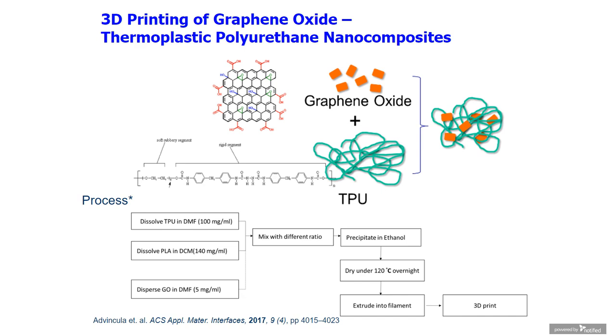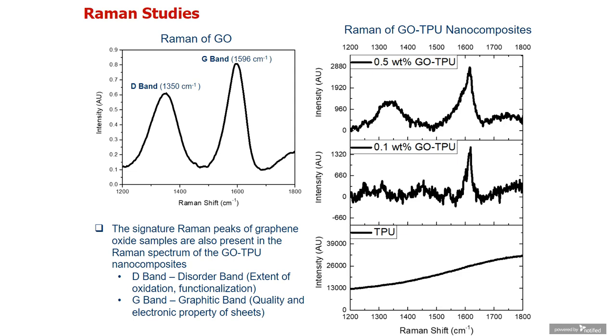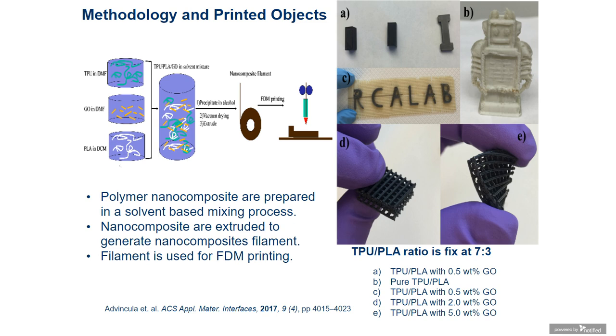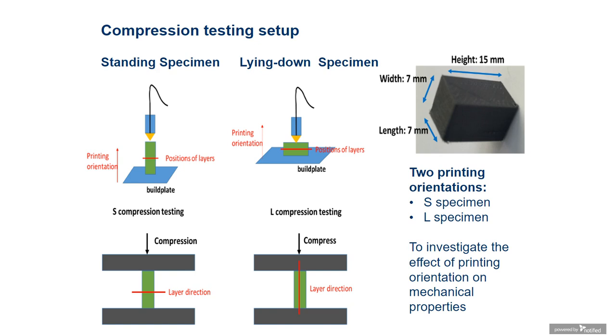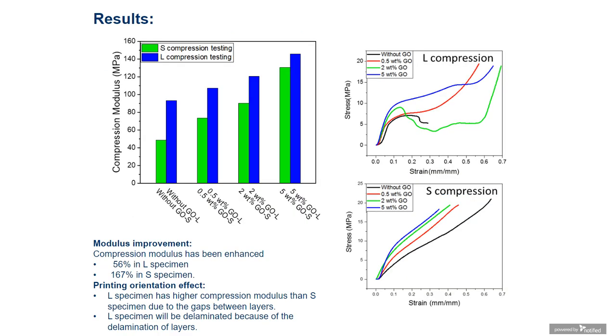So the interesting thing is we then took this TPU, we added graphene oxide, and we were able to demonstrate that it has good blending properties. We 3D printed them, and based on the amount of graphene oxide, we can confirm that we have various types of thermomechanical properties as shown in this PowerPoint presentation.